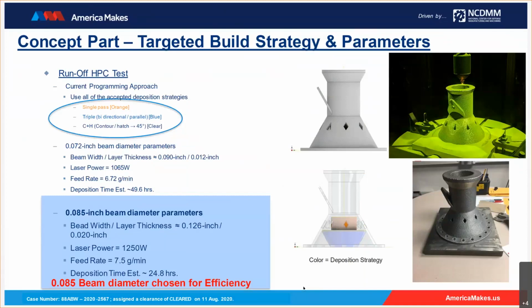feature-based DOE. So if you look at this part, the color that you see in the bottom right depicts the different build strategies that have been used to build different sections of the part. And what we have done is we have introduced features within this in terms of holes, in terms of wall intersections, in terms of walls with different thicknesses, so that we can actually extract these features out when we need to create the DOE. So we were partially successful in building this. Some parts build very well, some parts didn't build as well. But that was the point in terms of optimizing DOE based on the feature of choice. Neil, if you could go to the next chart.